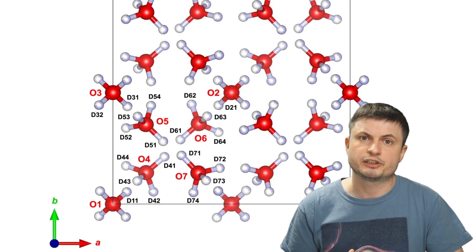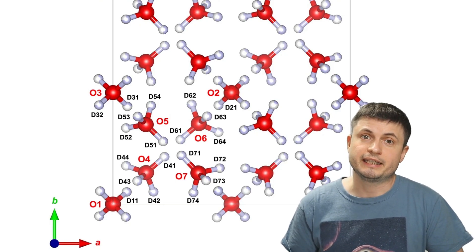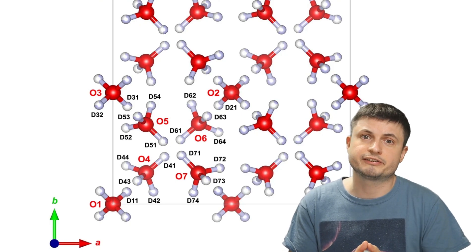In this particular case, the scientists were able to create this using another form of ice known as ice 15, and then cooling this down to about minus 170 degrees Celsius, and increasing the pressure to about 20,000 atmospheres. Which, by the way, is also something we find inside planets like Neptune and Uranus.